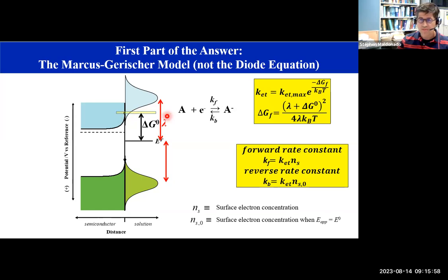This horizontal bar here in yellow represents the overlap at the conduction band edge, the bottom of the conduction band of the N-type semiconductor at the interface. It's literally the overlap in that horizontal slice that dictates the charge transfer rate constant, and that's what's shown over here. For those of you who like a more molecular description, this is the classic Marcus description of a charge transfer rate constant between donor acceptor molecules. It's the same thing.